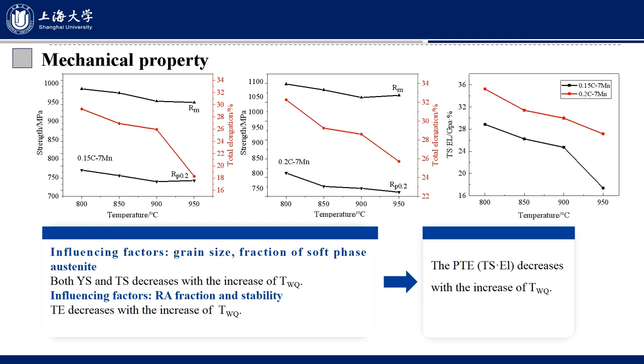Both yield strength and tensile strength decrease with the increase of water quenching temperature, and the influencing factors are retained austenite fraction and its stability. Total elongation decreases with the increase of water quenching temperature. And the product of tensile strength and elongation decreases with the increase of water quenching temperature. So the best water quenching condition is set as 800 degrees C.